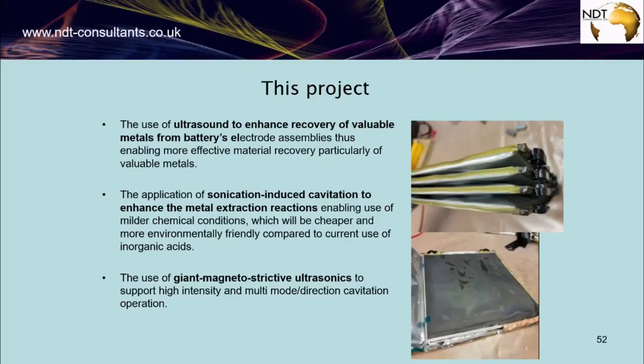So with ultrasound, we are hoping to use just a very mild solvent or any liquid, and ultrasound will be used as a catalyst to dissolve that organic binder between the active material and the metal. We plan to use ultrasound in this case, either just ultrasound with a resonance frequency for the organic material to break the bonds, and also we want to use ultrasound to produce cavitation. As you know, cavitation produces a lot of pressure, a lot of temperature in a liquid. And this mix of pressure and temperature will break the chemical bond of the organic binder.